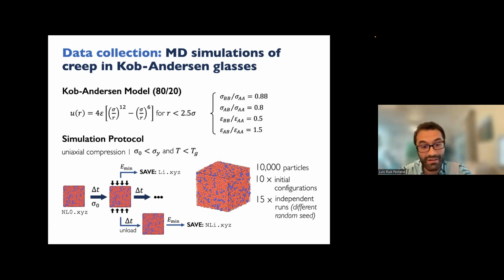Now, for each initial configuration, we perform 15 independent runs. Okay, the difference between one run and another: if you know anything about molecular dynamics, it is actually a deterministic algorithm. So what we do here differently is that we assign a different random distribution of velocities to the particles, right? So again, the configuration is the same. When I say configuration, it is the X, Y, Z positions of the particles initially, but the distribution of velocities is different. So that leads to actually different response of the system.